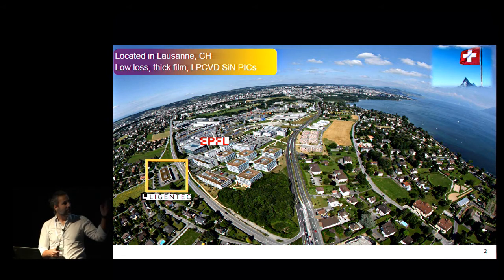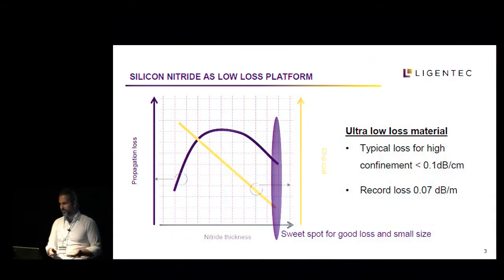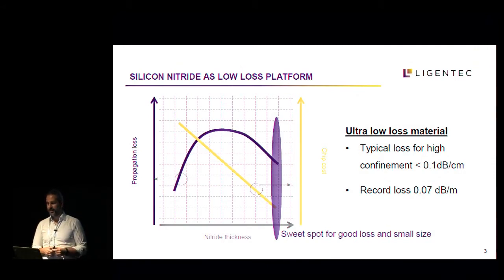You can see our location is opposite of the EPFL facilities, and we have a very nice view to the Lac Léman. Ligentec specializes in high confinement of thick silicon nitride, which gives certain benefits. The main motivation for high thickness silicon nitride is that as you increase your nitride thickness, you have the benefit of dropping your chip cost because your chip becomes smaller and reducing dramatically your propagation losses.